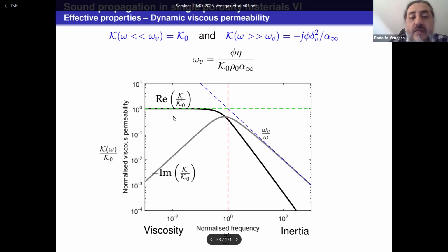So we're in a viscous dominated flow regime, and for frequencies much higher than the Biot characteristic frequency, we are in an inertia dominated flow regime. The imaginary part, minus the imaginary part, has a peak around the Biot characteristic frequency, indicating that this is where the sound energy dissipation is maximum.